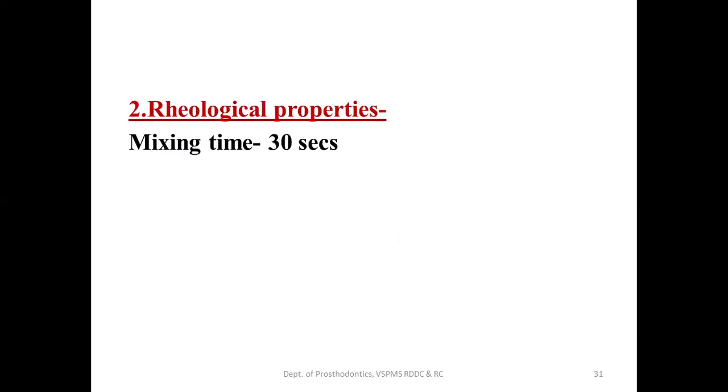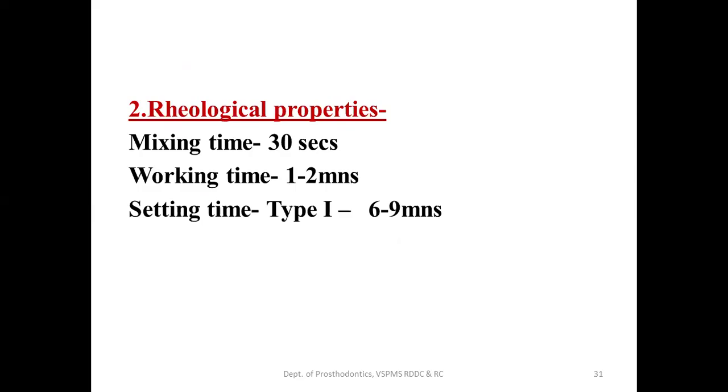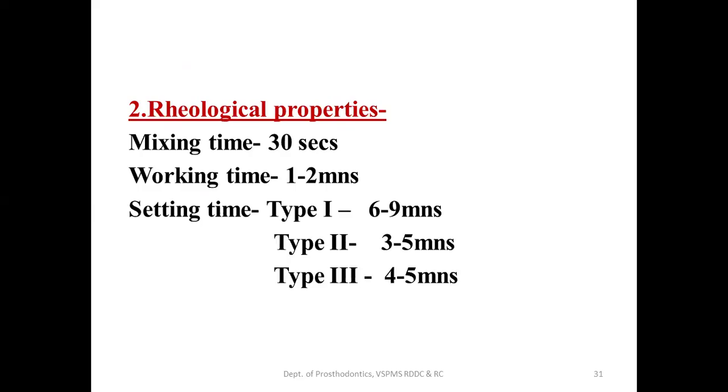Now, the rheological property: the mixing time is around 30 seconds. Working time is 1 to 2 minutes. The setting time for type 1 is 6 to 9 minutes, for type 2 it is 3 to 5 minutes, and for type 3 it is 4 to 5 minutes. Here the consistency is thinner, that's why more time. Here the consistency is thick, that's why less time. Again here the consistency is a little thinner as compared to type 2, that's why more time. So you can remember likewise.